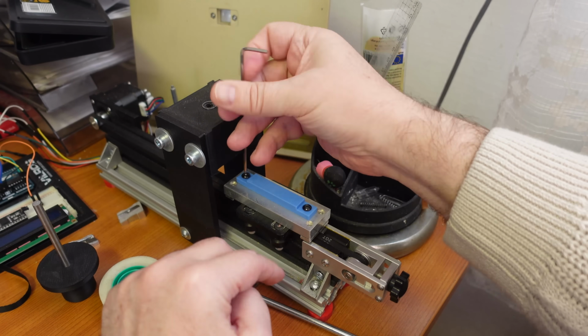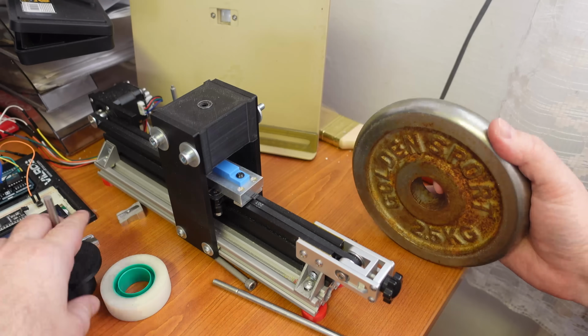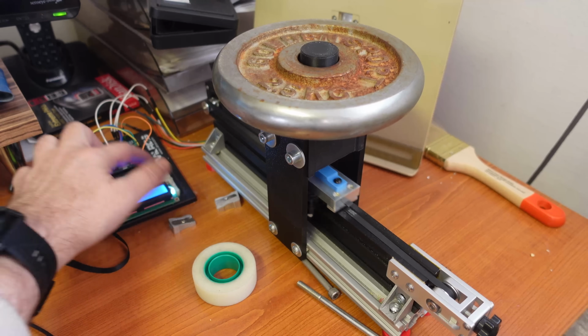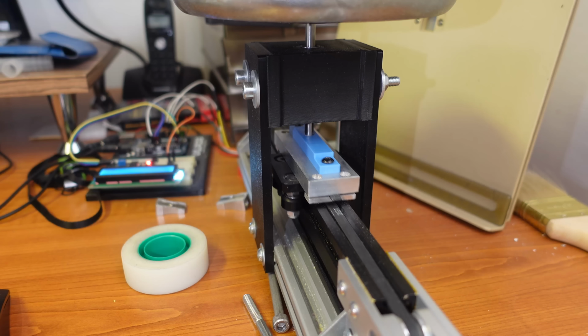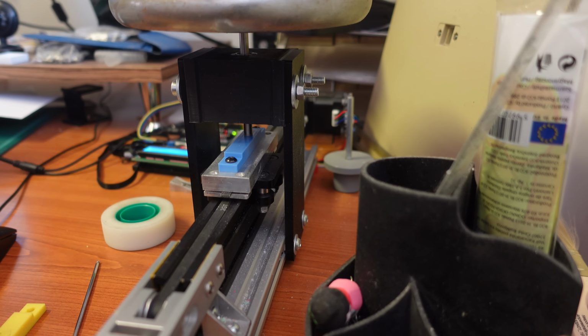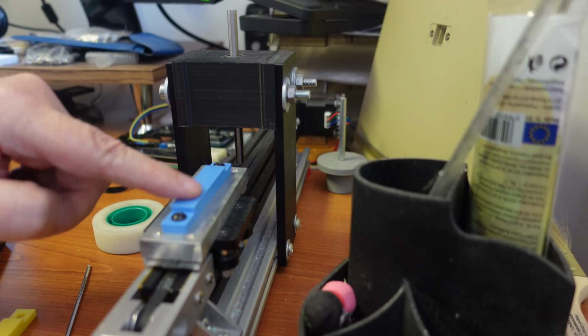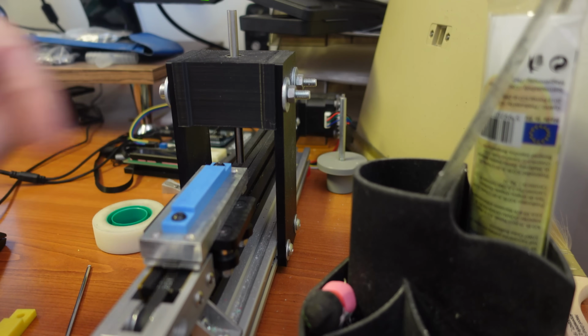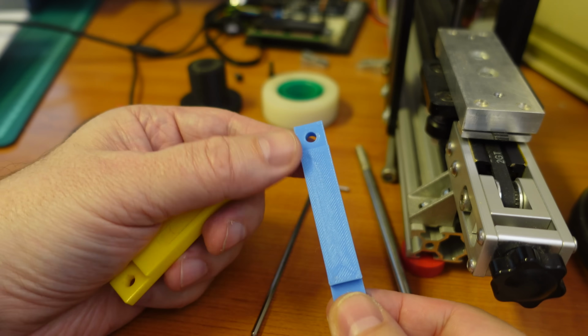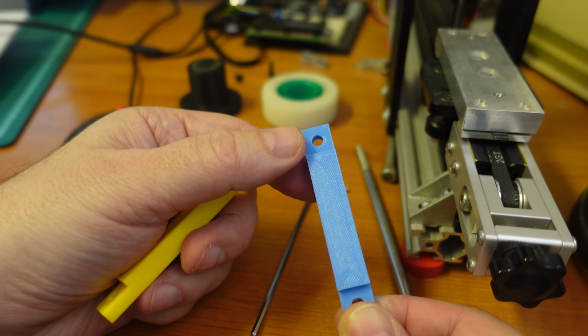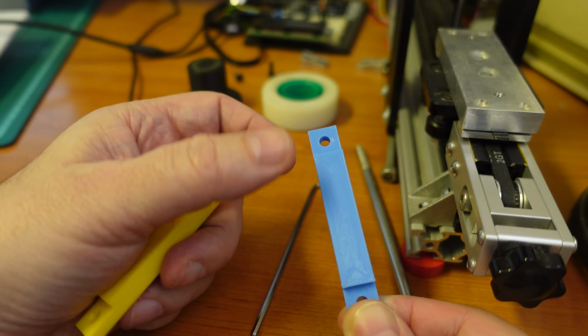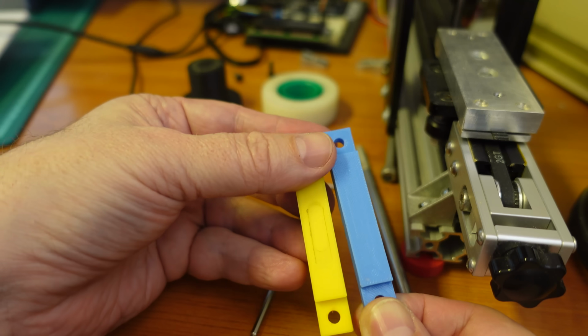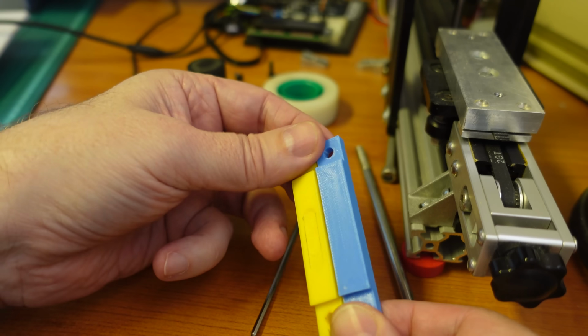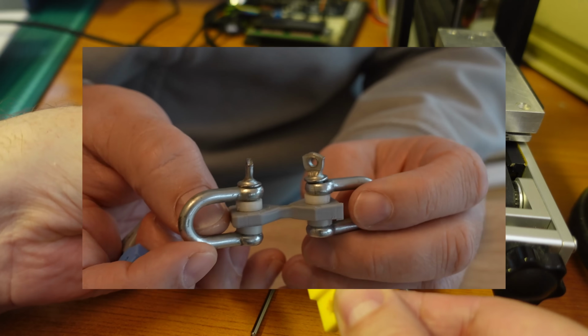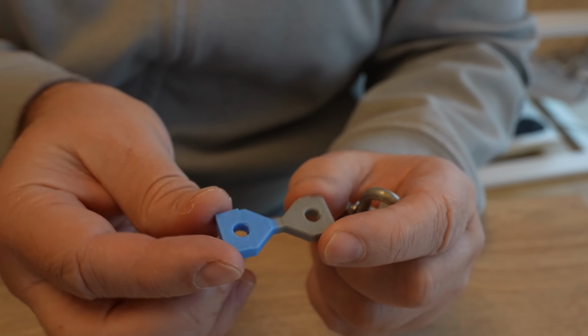This is my wearing test, presented in a separate video, and if you watch that video, you know that the TPU is very wear resistant material. Just checking if this is the case with this one too. After 3000 repeats, just some dust, and basically no visible marks on it. And I already tested this, so the TPU is very wear resistant material, and this TPU is no exception here. Usually I get something like this, you can check that video. And from now on, these are my regular testing methods for TPU filaments.